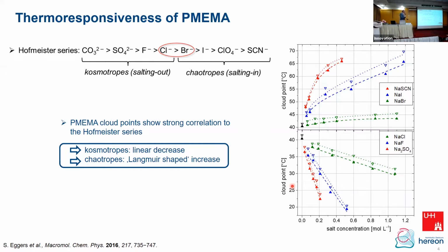There are two sorts of salts: the so-called cosmotropic salts and the chaotropic salts. The cosmotropic salts lead to more order, in the sense that a phase separated structure has less entropy in total compared to a homogeneous solution. So you introduce order by the so-called salting out effect. That means the presence of the salt makes the solvent less friendly to the polymer, and the polymer starts to precipitate at a lower temperature when you heat up the solution, because the phase separation occurs at high temperature in these systems. The situation is different for the chaotropic salts. There, the salts help the polymer to stay in solution, even at temperatures above the lower critical solution temperature in pure water. That's what you see here on the right-hand side in this slide.